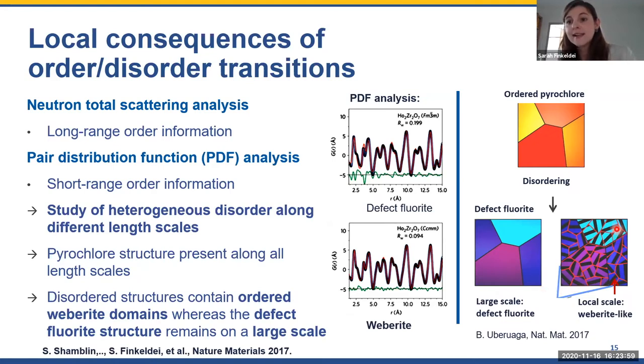So at the local scale, we obtained Weberite domains. You can see here the PDF analysis where we tried to fit our black data with a defect fluorite model. And you can see all the discrepancy in the data. At first my collaborators told me, Sarah, you just prepared awful samples. So this is just not working out. And then after a while, when we dug a little bit deeper, we found that we can actually describe the data that we collected extremely well on the local scale with a Weberite structure model. So what's actually happening is that at the local range, we are still observing a higher order structure than a defect fluorite structure, but at the long range, we have a more disordered structure, which is a defect fluorite structure.